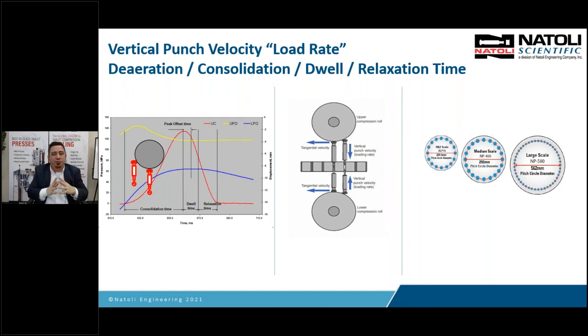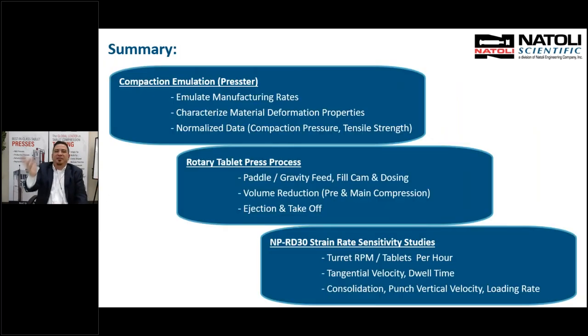And you'll notice with new presses today, the pre-compression roller diameter is the same as the main compression. Why? Because pre-compression wants to get the air out and consolidate. So the larger the roll, the more effective it is. Okay. All right, so a quick summary. We talked about the compaction emulator, which is the Presster. We can emulate manufacturing rates up to 2 meters per second. We can characterize the deformation properties. Is it dominant elastic? Is it dominant plastic or brittle? That allows us to formulate with the appropriate excipients to make a robust tablet at high speed manufacturing? We can normalize the data for pressure, tensile strength, solid fraction, and so on.